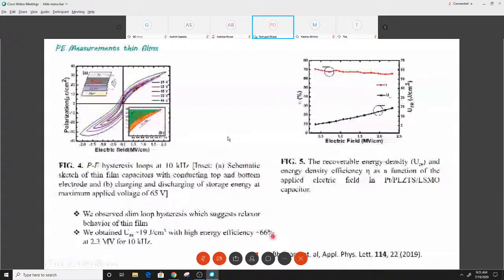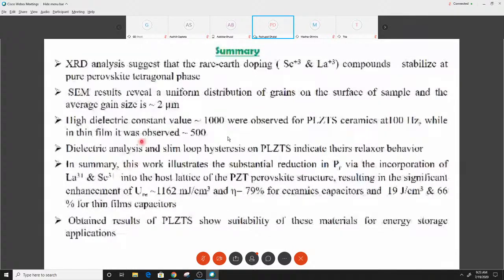This is the summary. Our work illustrates a substantial reduction in the remnant polarization and an enhancement of spontaneous polarization with the lanthanum and scandium substitution in the PLZTS. That results in a significant enhancement of the energy storage capacity and efficiency of ceramic and thin film capacitors. So our grown materials can be suitable for the energy storage application.